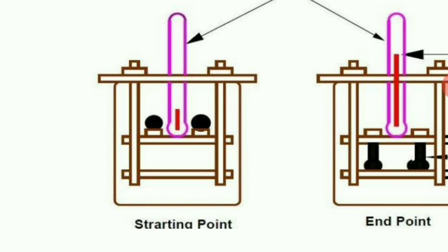This temperature is maintained for 15 minutes, after which the balls are placed in position, and then the temperature of the water is raised at 5 degrees Celsius per minute with a controlled heating unit until the bitumen softens and touches the bottom plate by the sinking of the balls.